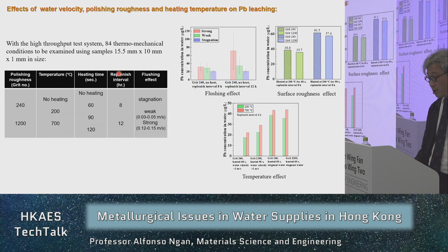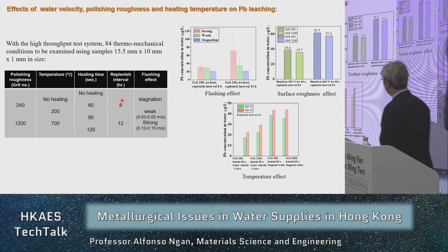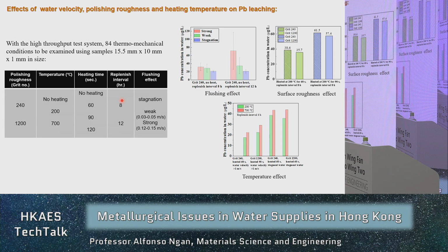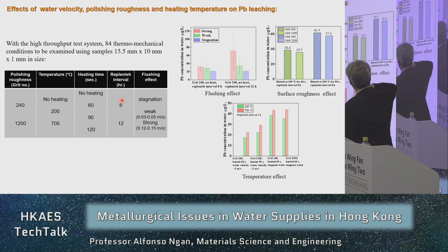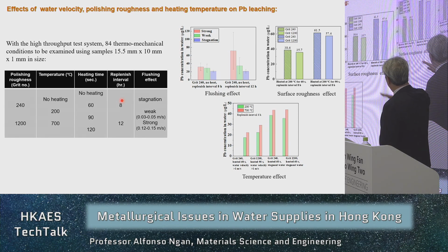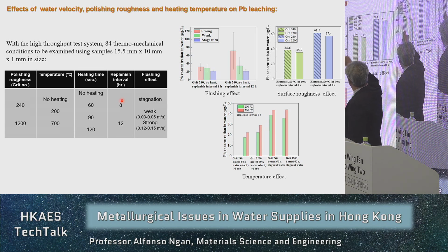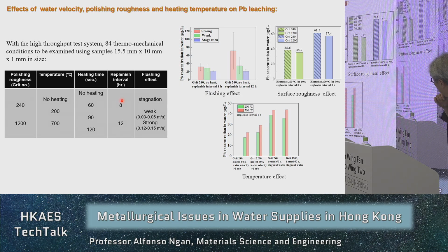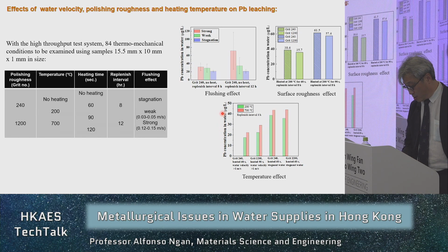And that's also part of the study scheme as well. We have different polishing conditions. We have different heating conditions. We even have different flushing effects, so either no flush or strong flush or weak flush, or even replenishing intervals. And those are just snapshots of some of our results. For example, for the flushing effect, if we flush strongly, then more lead will leach out. For the surface roughness, if we polish more, then the lead leaching will be slightly higher in this case. For the temperature, if we heat at a high temperature, then more lead leaching will occur.